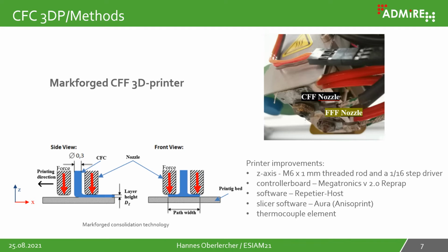For the first analysis of the consolidation of 3D printed continuous fibers, we used the Markforged technology, a Mark I 3D printer, but we made some improvements. For the Z-axis, we used a special threaded rod for better resolution. We also used a controller board to control the process parameters, because Markforged works with the Eiger software, and the Eiger software is a kind of black box, so it isn't possible to control printing speed or layer height or anything else. We also used open source software to control the printer. We control it with Repetier-Host, and as slicer software we used the Anisoprint slicer.